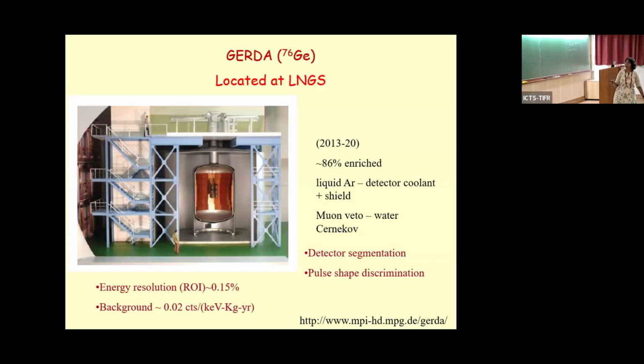And this is surrounded by a water Cherenkov to get the muon veto. Germanium gives you the advantage that you can have a segmented detector, so you can even have a large sector with segments, so you can have more localized interaction points. And pulse shape discrimination can be done because different particles will give you a different kind of reaction. So based on that, you can also discriminate the background.